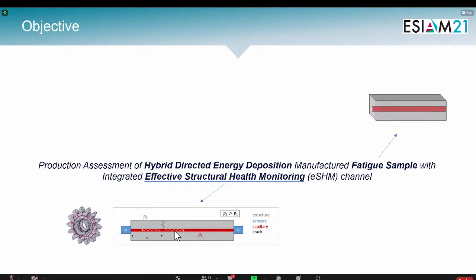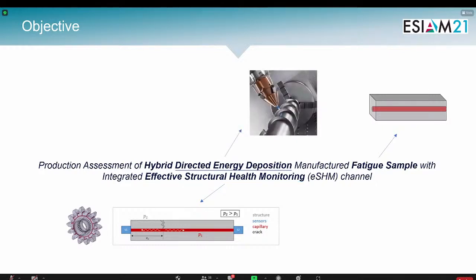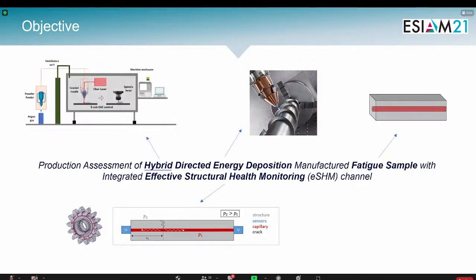It creates the propagation of pressure waves in these capillaries that can give us information about the health of the structure. Now, the production of this fatigue sample will be done with directed energy deposition that relies on the simultaneous laser and powder delivery. And it will be done with a hybrid in-house developed machine at the VUB called the MICLAT machine, that has one part used for additive operations for the printing process, and that can also switch very fast to subtractive operations such as milling and drilling, and it's a 5-axis CNC control machine.